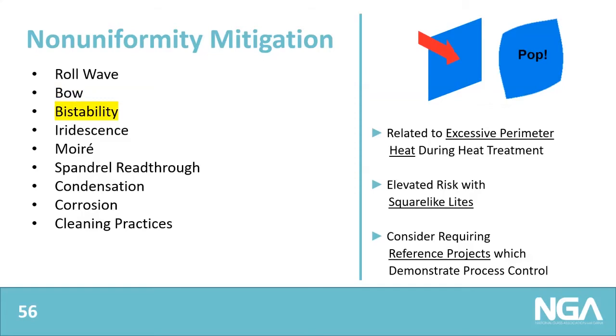Bistability is a situation where you could press on the center of a piece of glass, and the glass could suddenly move into a deflected state with a loud sound. And then if you press in the opposite direction, the same thing could happen in the reverse configuration. The situation is related to excessive perimeter heat during the heat treatment process, and it's a risk with square-like glazing.